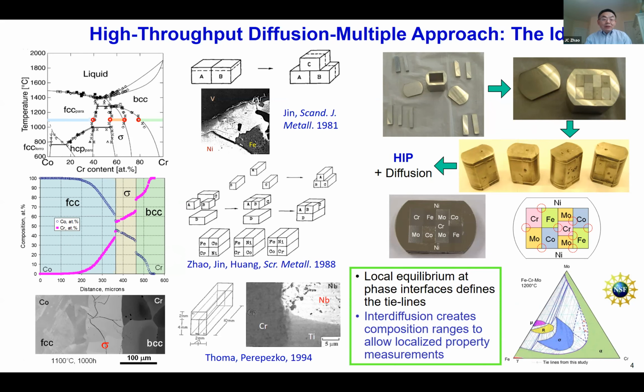So this has been in existence for many years before me. And then I learned how to make diffusion triples from my former advisor, Professor Jin. And so this is how we basically put the three pieces together so that we can take advantage of the diffusion among three of them. I even made a diffusion triple as part of my master's degree dissertation at that time. In the US, John Perepezko and Dan Thoma did one triple in 1990, published in 1994. So when I was at GE, because it's very time consuming to make triples one at a time, I developed this method to combine many diffusion triples and diffusion couples into a single sample. I call it diffusion multiple.